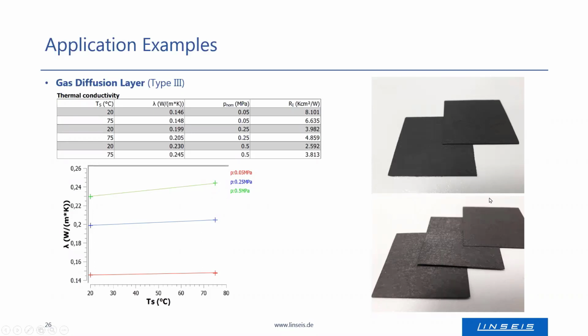In the images, you can see such gas diffusion layers, measured in dependence on the temperature and on the contact pressure. The sample temperature was increased from 20 degrees Celsius to 75, and the contact pressure was set to 0.05, 0.25, and 0.5 megapascal. For each sample temperature and contact pressure, 3 different thicknesses were measured.